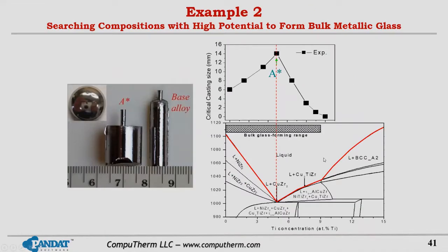The second example is to search compositions with high potential to form bulk metallic glass. About 10 years ago, we did some work using phase diagram CALPHAD calculations to search compositions for bulk metallic glasses, and we found that most compositions with high potential to form bulk metallic glass are at low-lying liquidus temperatures.